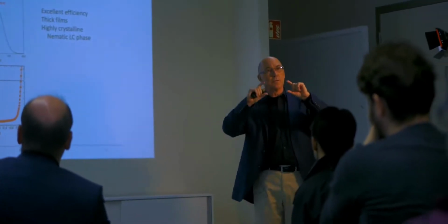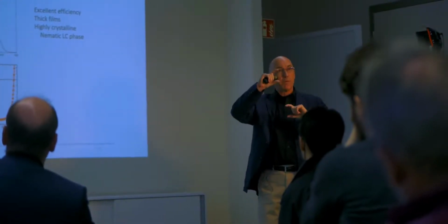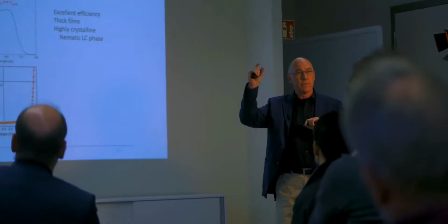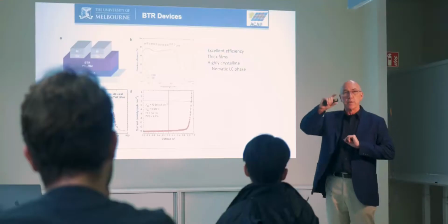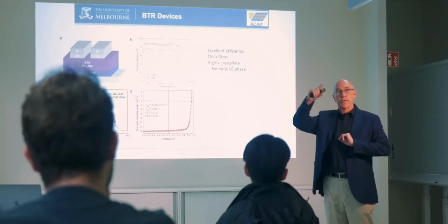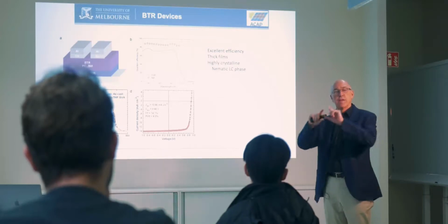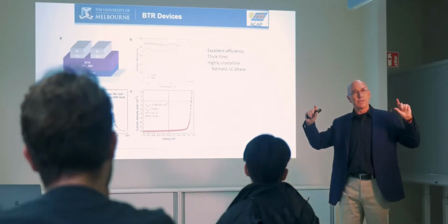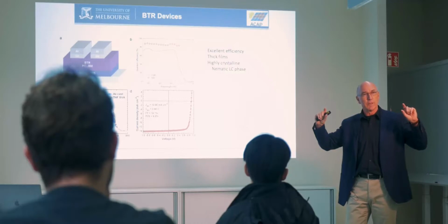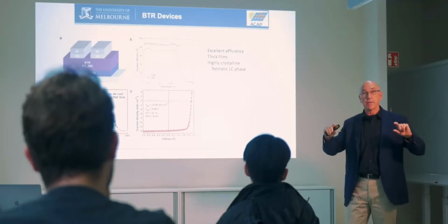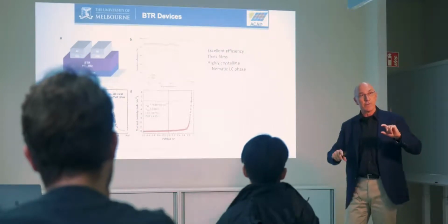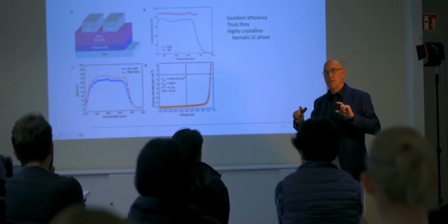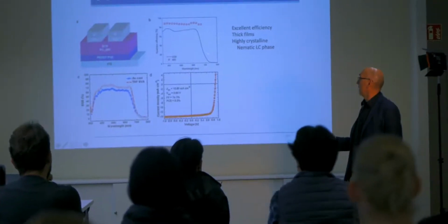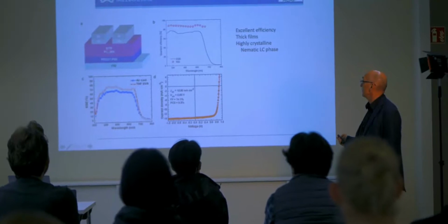So you want that to, if you can print thicker and you've got a variation of, if you've got 300 nanometer and you vary by 50 nanometer, you go from 300 to 350 down to 250, you probably won't change the efficiency of your overall cell. If you've got 100 nanometer thick and you're going from 100 to 150 down to 50, then you probably have issues. And so having thick films was really important.